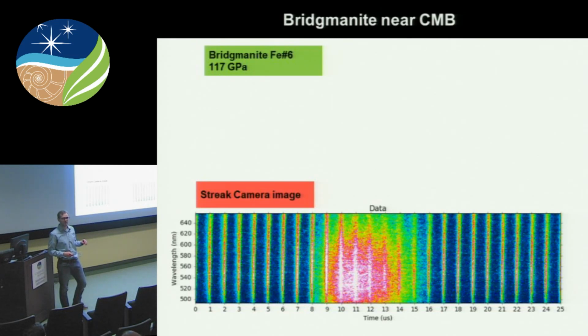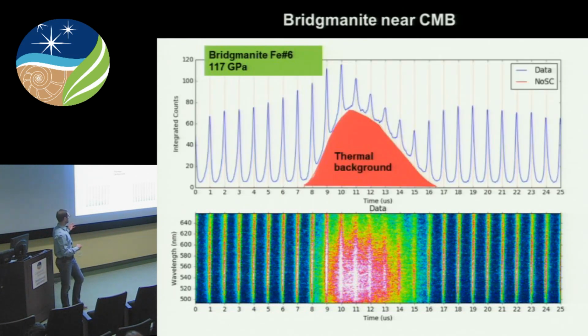So basically, in just one shot, we press fire, and everything happens instantly for us. So we get an image that looks like this, that contains information on the optical properties of our sample at low temperature, before laser heating, at high temperature from 6,000 to 3,000 Kelvin, and then as the sample is cold again. So we can now use this image to extract a bunch of information, and here is just integrated intensity over the wavelength range.